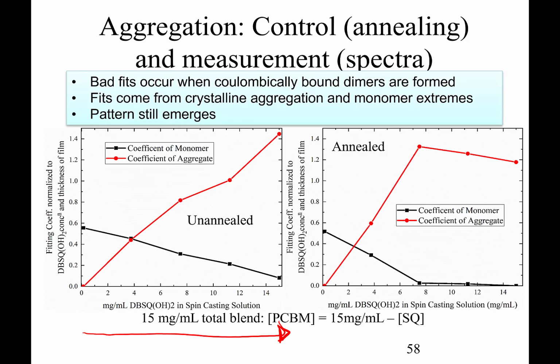And what we find is that at the maximum amount, the amount of monomer starts to drop down. It's a fairly linear drop. And what we also find is certainly the amount of aggregate, the amount of certainly dipole-dipole interacting species goes up. But this represents the aggregate in here at the moment. The fits aren't so good.